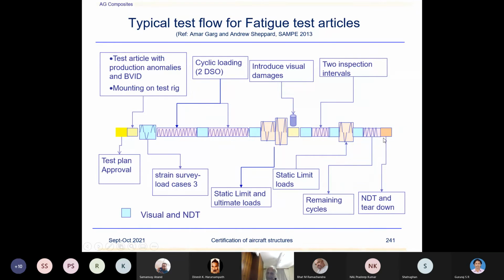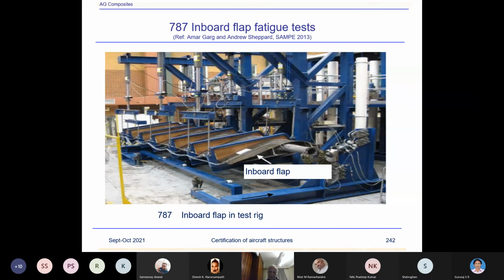And then, of course, NDT and tear down inspection. We found no damage done to the structures anywhere. And that is how, using the fatigue test article, the compliance was met for the fatigue test. This is just showing the flap, which is similar to the static test.